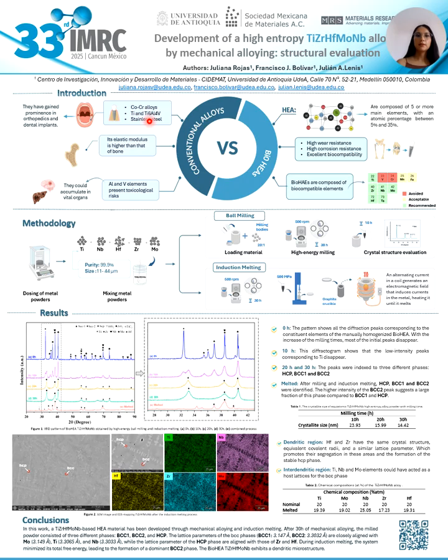However, titanium aluminum vanadium has some disadvantages. For example, its elastic modulus is higher than that of bone, leading to biomechanical incompatibility. Besides, its lower wear resistance can result in the release of metal particles under repetitive stress conditions, causing inflammation and damage to surrounding tissues. In addition, aluminum and vanadium elements present toxicological risk, including accumulating in vital organs such as the kidneys, liver, spleen, and brain, leading to negative health consequences.